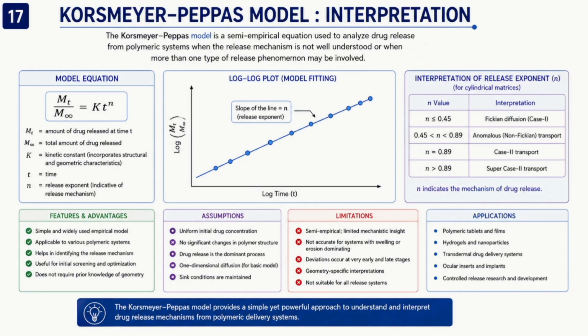So for the meaning of n, for a cylindrical system, the value of n provides the information about the release mechanism here. So when the n is around the Fickian region, the diffusion is the dominant mechanism here. As n increases into the intermediate region, we may observe the anomalous or non-Fickian transport here. So this indicates that more than one process may contribute here, such as diffusion combined with the polymeric relaxation or swelling. So at still higher n values, case 2 transport and the related mechanisms may become important here. So the exact interpretation of n depends on the geometry of the dosage form. So we must never memorize one universal range and apply it to every system.